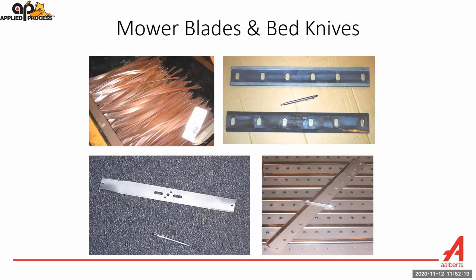On the lower right, you see what's called a bed knife. That goes on a reel-type mower that would be used on a golf course. At 48 to 52 Rockwell C, we can take one of those bed knives, put it in a vise, and bend it at 90 degrees, and it will not break. If it were oil quenched and tempered to the same hardness, it would break probably at 15 to 25 degrees of bend. That's the thing about these blades. You do not want them to shatter. You want them to distort and absorb energy.